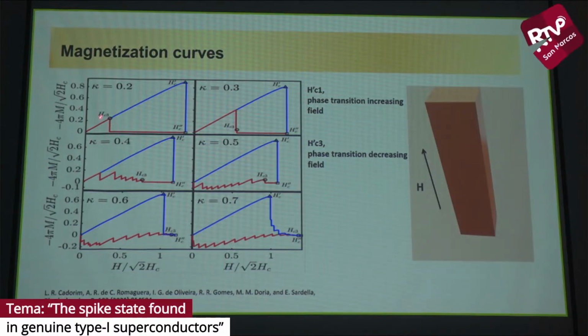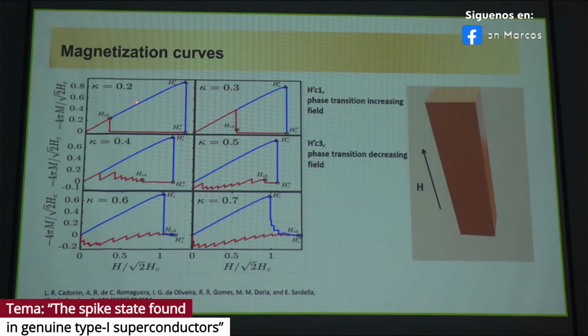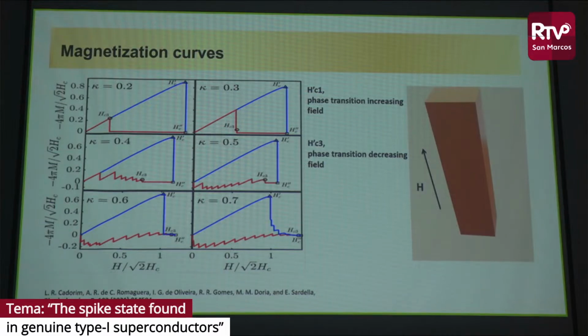But here we can see that for a very small value of the Ginzburg-Landau constant, increasing the applied magnetic field, we change to the normal state, and decreasing the applied magnetic field, there is the transition from the normal to the Meissner state, and both curves are still the same. Okay. With these magnetization curves, we could build that diagram.